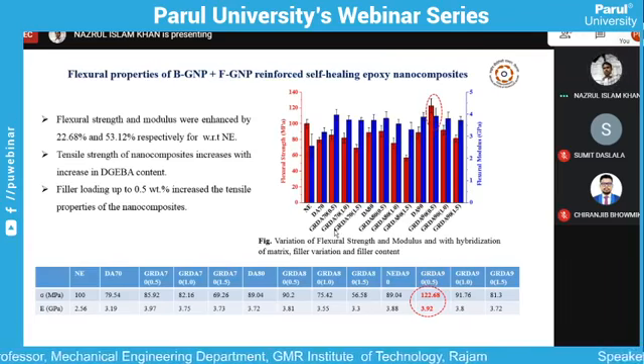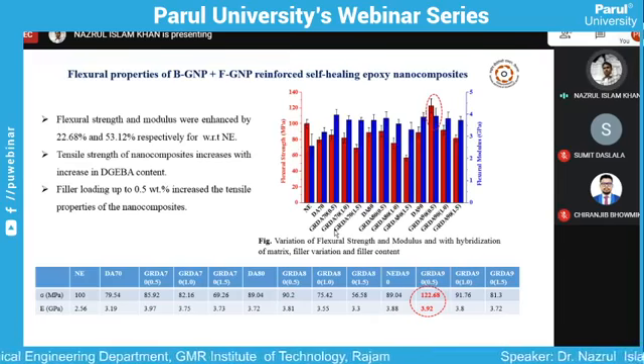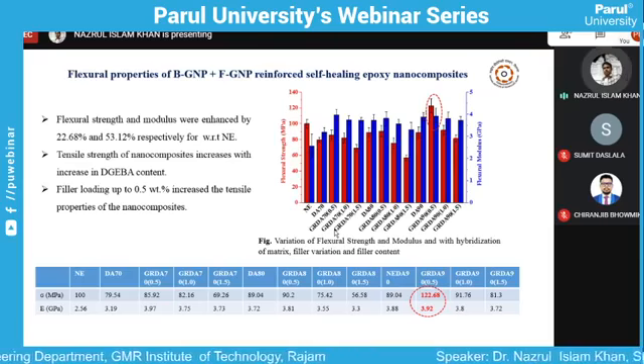This enhancement was there because the bismaleimide on furfuryl amine functionalized graphene were able to form covalent bonding with the matrix. Due to that, we were able to get this kind of enhancement.